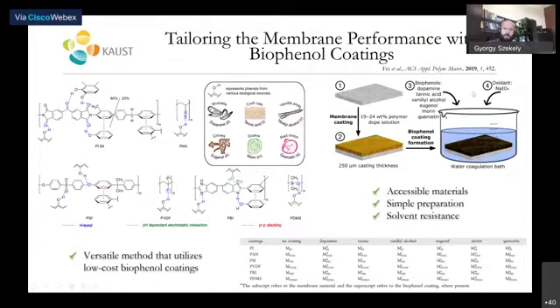So here you can see the general procedure that we follow. You take a substrate, you prepare a membrane on it, which is a very loose nanofiltration membrane, an ultrafiltration membrane, and you use this biophenol coating to close the pores of your membranes and therefore bring it down from a loose nanofiltration or ultrafiltration to a tight nanofiltration membrane. And the different supports that we tried are not necessarily green or sustainable, but the coatings themselves are sustainable.